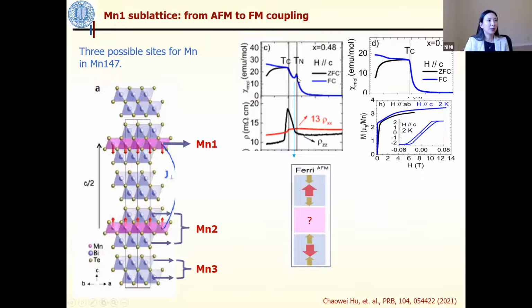So if we think about that, we will say between the TC and the TN, between these 2 phases, we are entering into a so-called ferrimagnetic and antiferromagnetic case, right? What does that mean? That just means your manganese 1 sublattice is antiferromagnetic to itself. Your manganese 2 sublattice is antiferromagnetic to itself. And these 2, manganese 1 and manganese 2, are antiferromagnetic to each other.